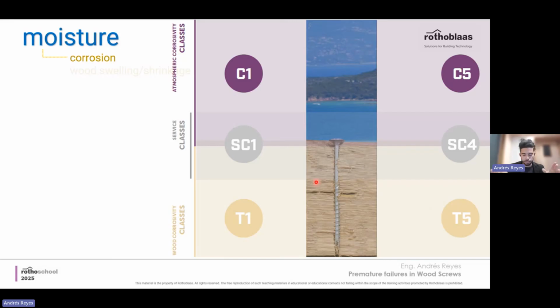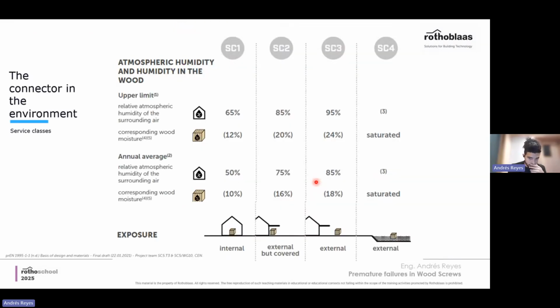whereas North American standards tend to have only dry and wet conditions, with the threshold at 19. So this is more or less what service classes look like in Europe. And at least the new approach in the new Eurocode will give an annual average for what would be considered dry condition or service class 2: an annual average of 16% and an upper limit of 20% that cannot be surpassed by more or less 3 to 4 weeks.